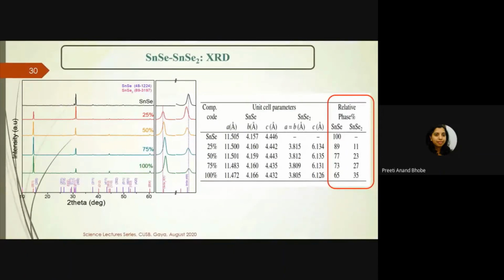As you increase selenium content, that second phase keeps growing, and when it is 100%, we expected this to be pure SnSe2, but we noticed that along with SnSe2, you still have a remnant phase of SnSe remaining in this material. And when one does the analysis of this XRD by the Rietveld refinement method, one finds that the ratio of SnSe to SnSe2 phase is changing considerably.